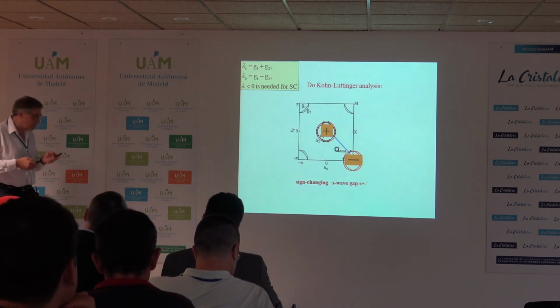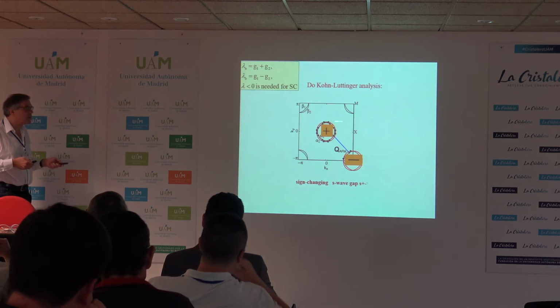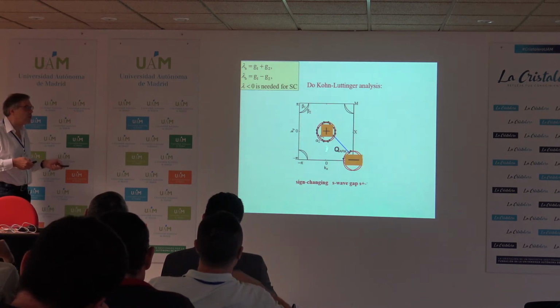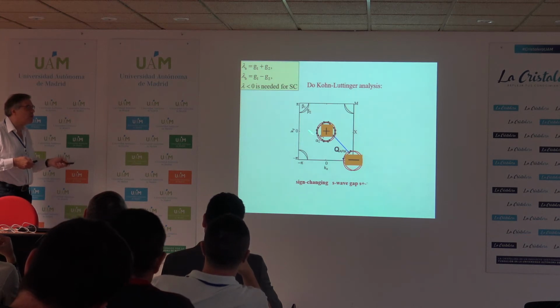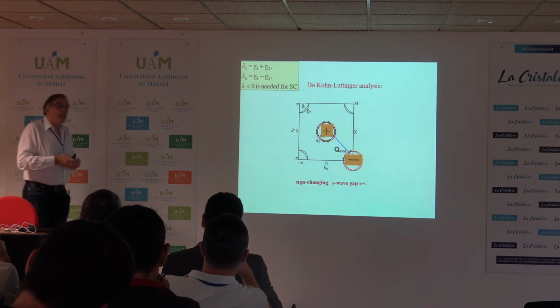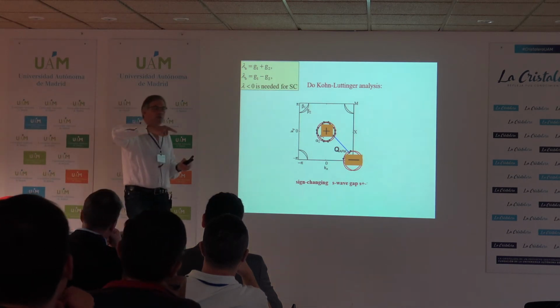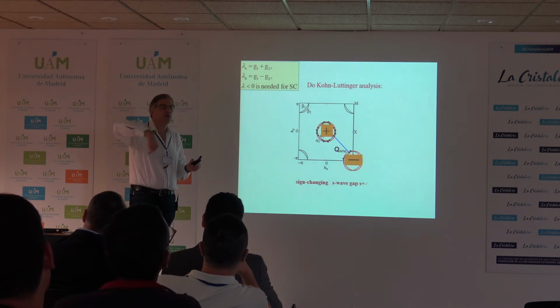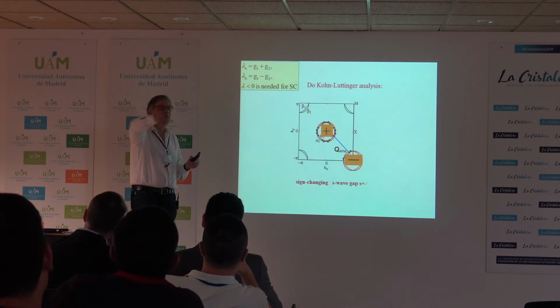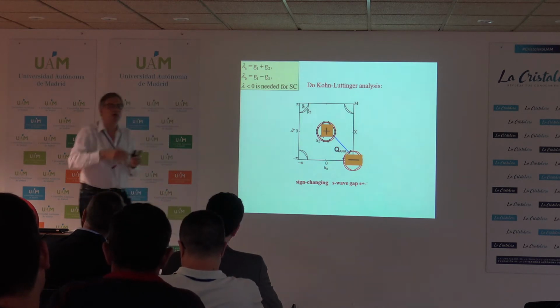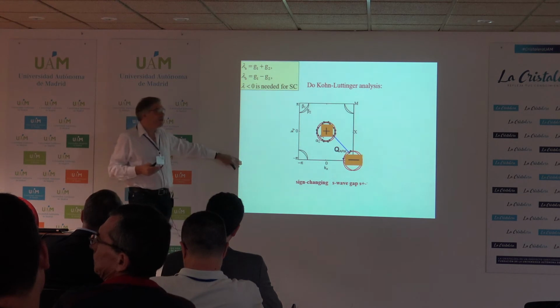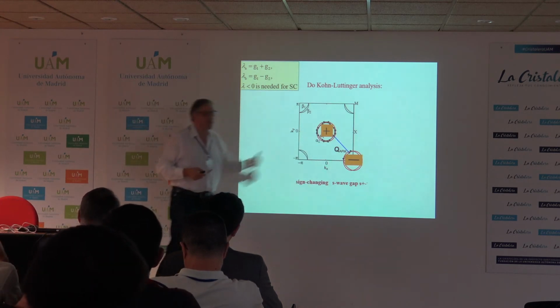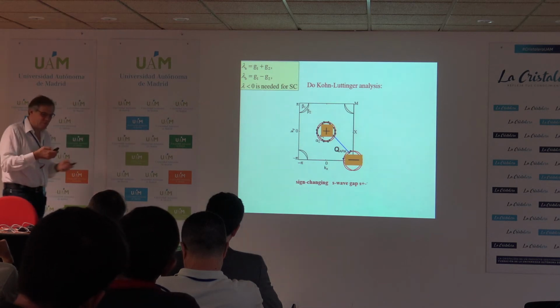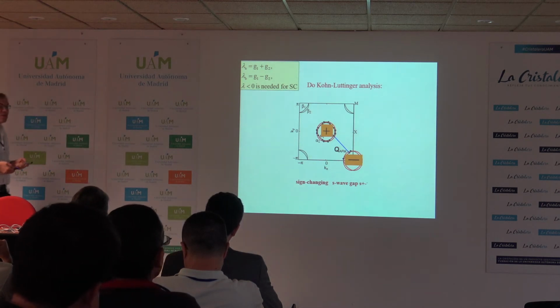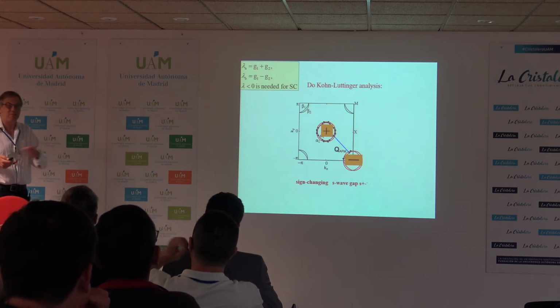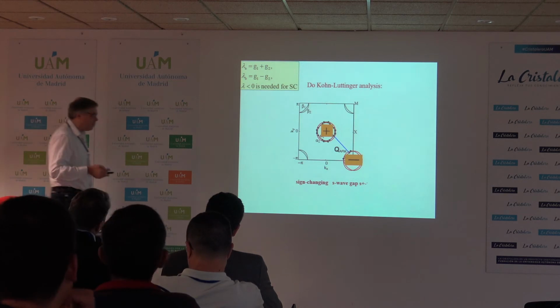So I ask the question what it means. It means that there is again sign change of the order parameter, but now between pockets. If I go along one pocket, the order parameter doesn't change sign. How do I determine the symmetry of the pairing state? I go along the Fermi surface, encircle zero in momentum space, and ask how many times the wave function changes sign. If it doesn't change sign, I call it S wave. So by this count, it's S wave. But because it changes sign between two different pockets, it has the name S plus minus, meaning that there are two different signs of S wave on the two pockets. And this again comes out instantly. You don't need to do anything besides 5 minutes of calculating of one diagram.